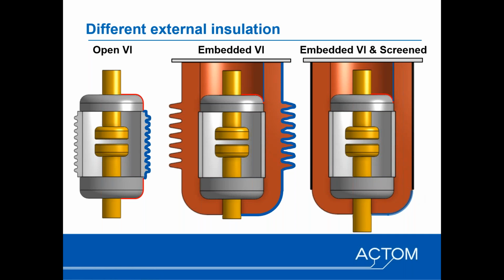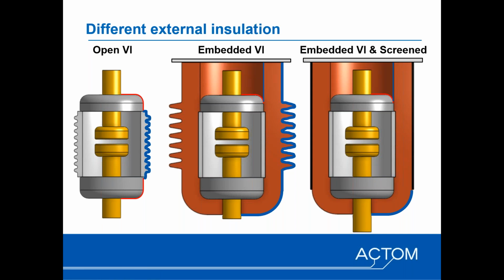So your exposed external creepage extends basically from the end of your earth shield. Now you may say this distance may be shorter than what you would normally have with normal embedded epoxy. But in terms of screened switchgear, all the connections to the high voltage components like bus bars and cable connections are done through screened separable connectors, which form an earth layer on the outside exposed to the atmosphere, where the inside surface is sealed off from the atmosphere, and is controlled by the interface fit between the screened separable connector and the actual switchgear module.